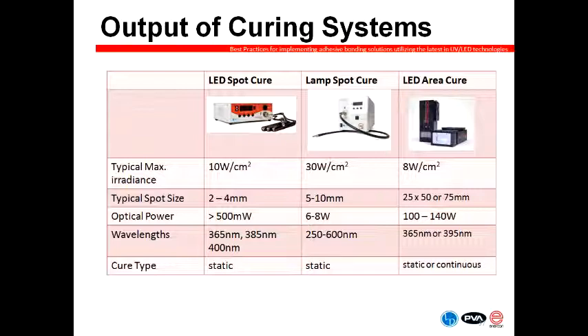So when we talked about the first point, we talked about the dose or the irradiance level. This slide here shows a comparison on the output of lamp and LED systems. And here I'm comparing LED spot cure to a lamp spot cure. If we look at the typical maximum irradiance from an LED spot curing system today, most LED systems can achieve up to about 10 watts per square centimeter, which is really more than enough irradiance for almost any curing application. One of the limitations, though, you'll see is that they're really limited to small spot sizes, and that's how we're able to achieve the high irradiance level, such as 10 watts per square centimeter, by using a lens to focus that energy into a very small spot.